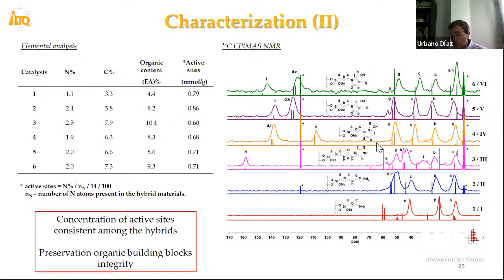Moreover, preservation of the organic moieties was confirmed by carbon NMR, which confirms the preservation of the organic fragments present in the structure, and from the silicon NMR the T species are also identified, confirming the effective covalent integration of the organic groups in the framework of the silicon architecture.